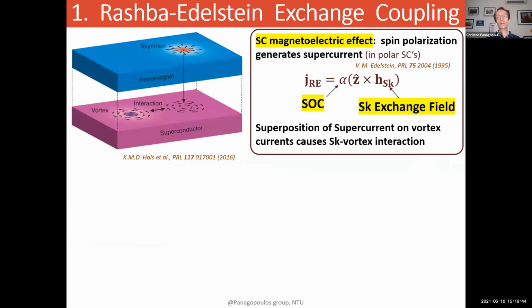The first interaction that you need to consider is the Rashba-Edelstein exchange coupling. That is essentially a superconducting magnetoelectric effect. So if you have a skyrmion in a ferromagnet sitting above a vortex of a superconductor, shown here in the schematic, then spin polarization will generate a supercurrent. And that supercurrent will be a function of spin-orbit coupling and the skyrmion exchange field. So a superposition of supercurrent on vortex currents would cause a skyrmion-vortex interaction.